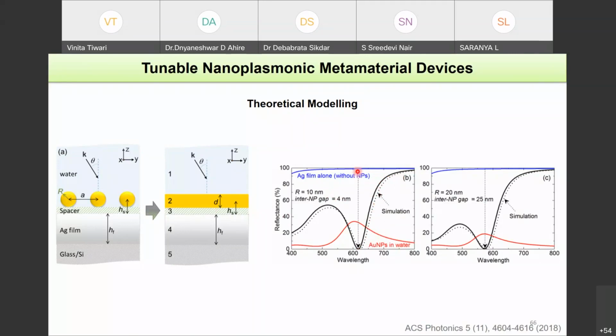So what is happening at this particular wavelength is very, very interesting, because when there is no nanoparticle, you have 99% of reflection. When nanoparticles assemble, you get 0% of reflection. So you're able to switch between a perfect reflector and a perfect absorber. And good thing is that by changing the size and the interparticle gap of the nanoparticles, you can actually change the wavelength of operation of this device.